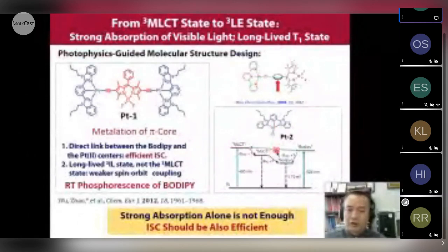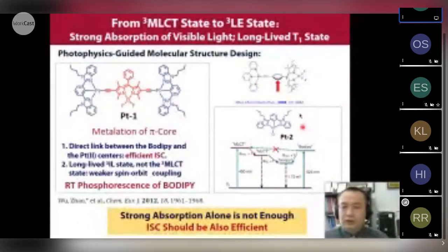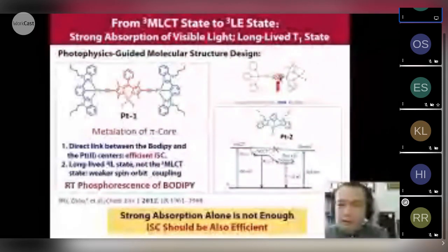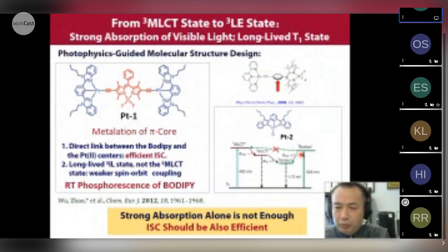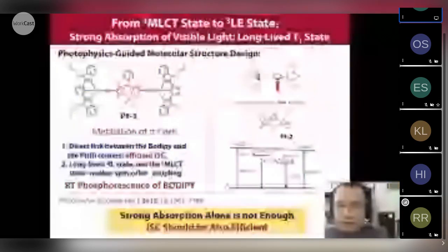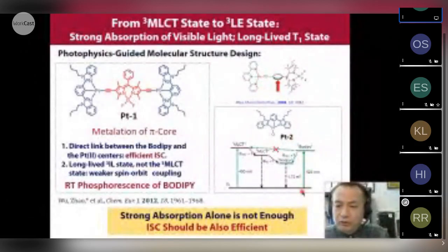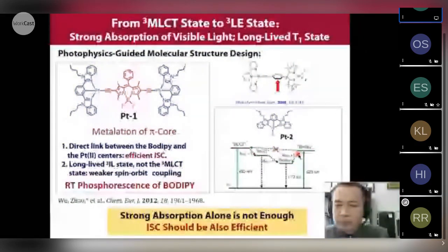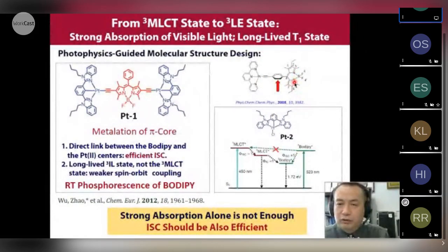It's not easy to prepare such a complex. Simply connecting a chromophore to a metal complex will not lead to efficient intersystem crossing. If we look at this molecule, actually this phenyl ring separates the BODIPY chromophore from the metal center. That means the intersystem crossing will be poor if we excite this part. So let's see the energy diagram. BODIPY is actually with lower energy than the metal coordination structure. So if you excite the BODIPY part, you also have strong absorption of light, but the intersystem crossing is not efficient. That means the energy will be trapped on this part. It will not give you high efficiency triplet production.